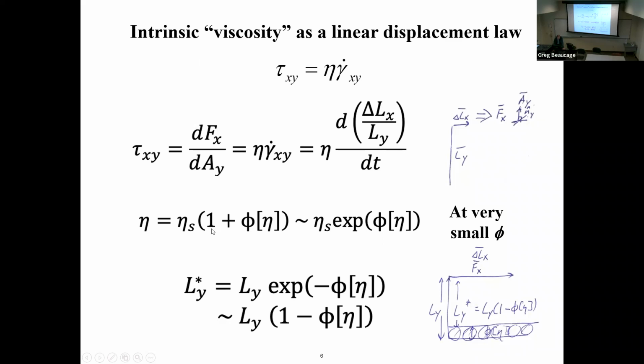They asked Einstein if there was anything he invented that he wished he hadn't invented, and he said it was this equation. So this is called the Einstein equation. For solid spheres, this intrinsic number is 2.5. For polymers, that number is significantly larger. We'll say why that is, but basically, if you take that equation, the Einstein equation with intrinsic viscosity instead of 2.5,